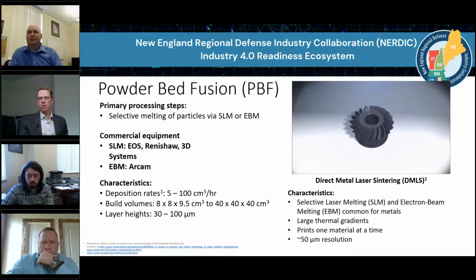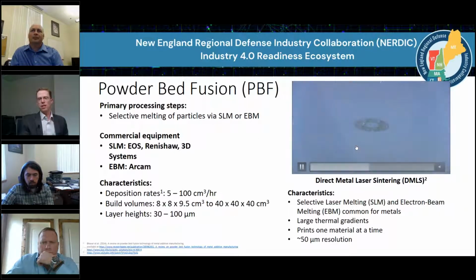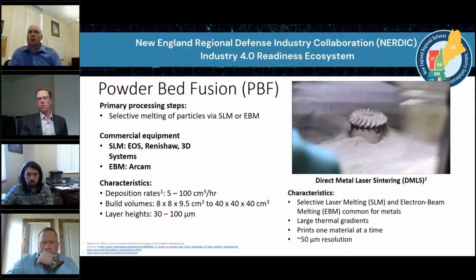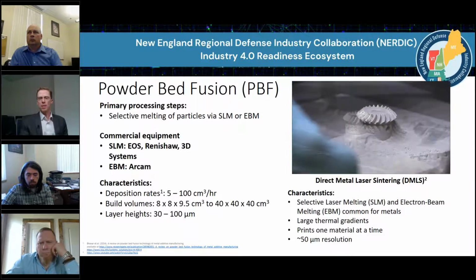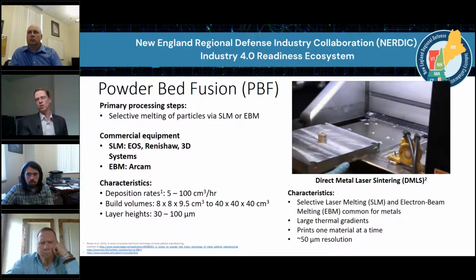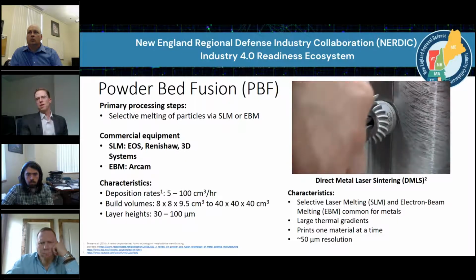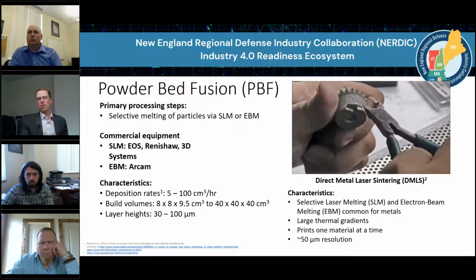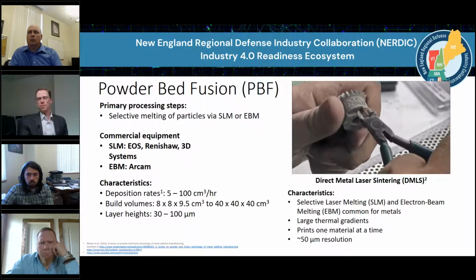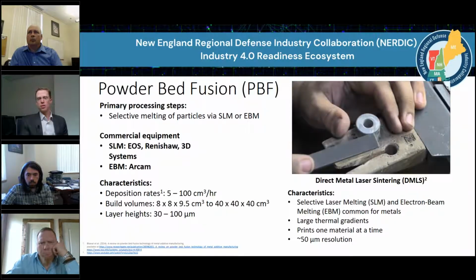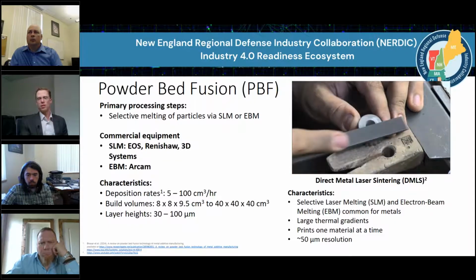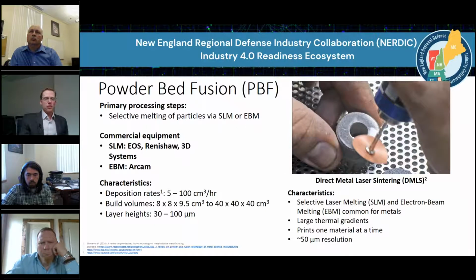So you have the part, and here's how fast each layer takes. Each layer is about 30 to 100 microns. Here the part is being removed from the powder bed, at which point you can do any sort of post-processing. Here they're taking off the thermal boundary to allow heat to escape, any sort of cleaning, finishing, and post-processing.